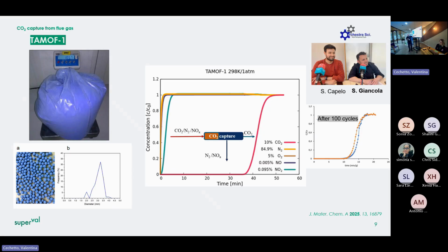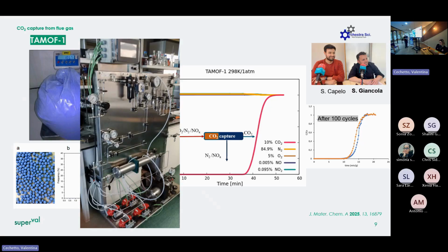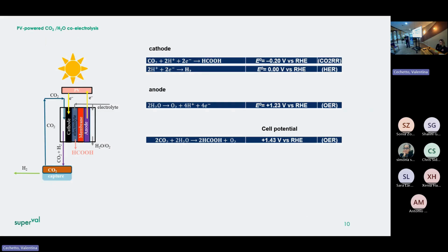The stability, we know, Stefano and Santiago ran over 100 cycles with good reproducibility and stability, retaining over 95% of the original performance. And this is scalable not only as a material, but also in actual devices. And now Orchestra, the company working with this MOF, has a pilot plant working in a multi-liter per minute continuous performance. So once this first part is solved, let's go to a second part.